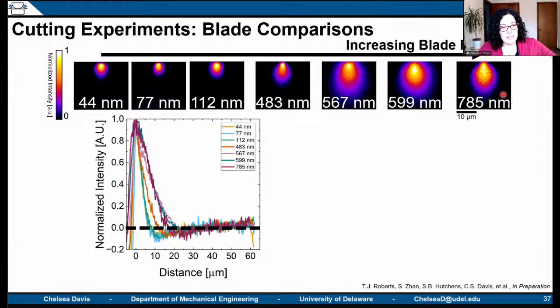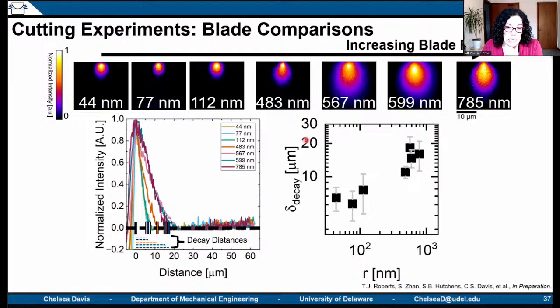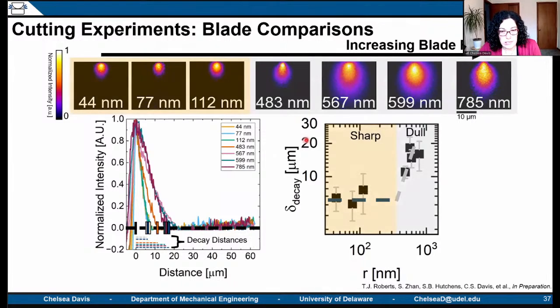And we can quantify this using the normalized intensity mapping. We can go through and say, okay, this is how large of a deformation zone we have as a function of blade radius, and get what we're calling the decay distance. And from here you can see a fairly similar relationship. I recognize these are 7 points, but you can see a fairly similar relationship between the sharp and dull blades having no effect and then a monotonic effect on this decay distance as a function of sharp and dull blades.